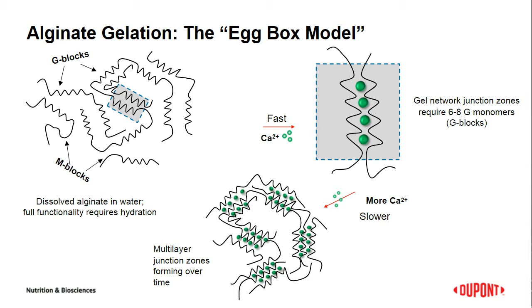This leads to a gel formation based on junction zones formed of 3 to 4 calcium ions with 6 to 8 G monomers. If an additional amount of calcium is added slowly, multi-layer junction zones can be formed over time, leading to further increased gel strength or even precipitation.